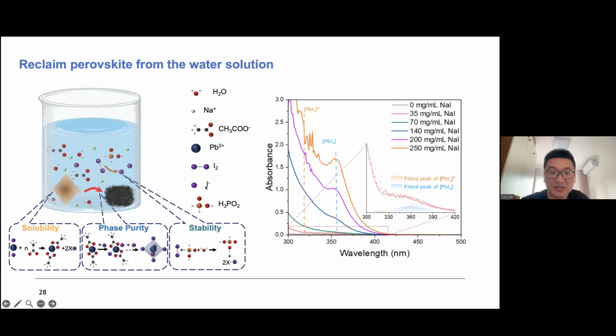And the motivation is just to introduce the iodide ions. You can see here from the absorbance, when we increase the iodine ions inside the solution, we can clearly see the appearance of the PbI3, which is the structure for the corner sharing of the lead ion coordination in the solution. So we combine them all; the three additives are trying to solve three different problems, that is the solubility, phase purity, and also the stability issues in the perovskite solar module. And combining them all, we can now recycle the perovskite with just the water solution.